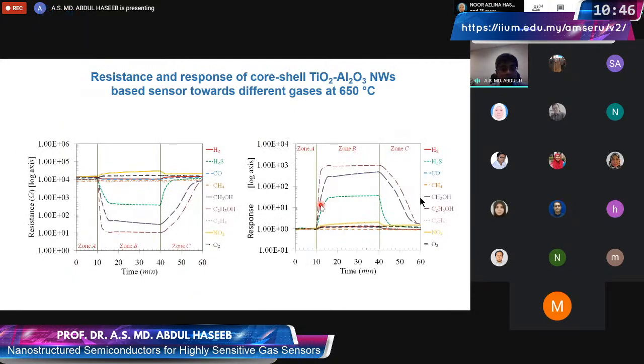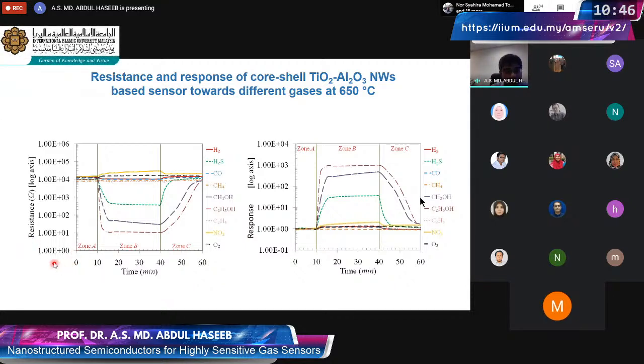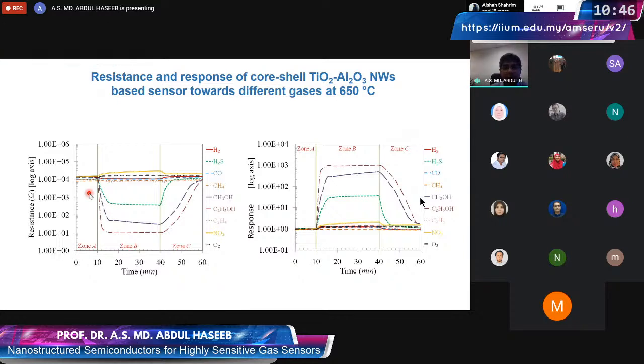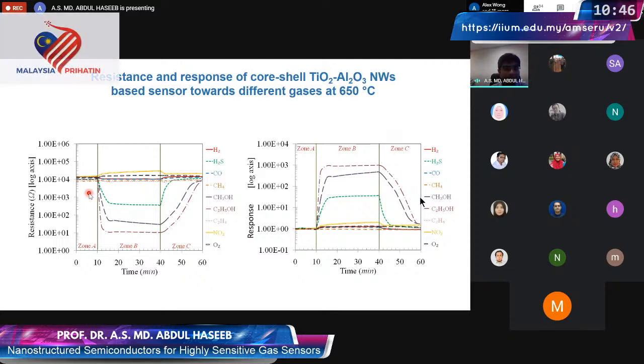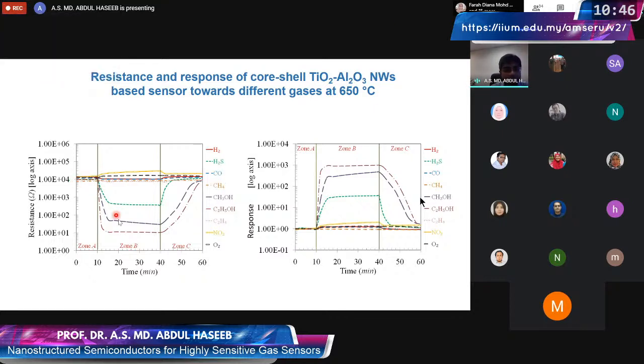Okay. Now let me show you the initial result. So we basically measure the resistance, and we introduce gases, and we measure the resistance as a function of time. We divide it into 3 zones. Zone A is the zone where we have the carrier gas, and for this measurement we use nitrogen as the carrier gas, which is not an active gas and widely available in the atmosphere. And when we measure the resistance, we get a particular value for this material, then we introduce different gases, and that is represented in zone B.